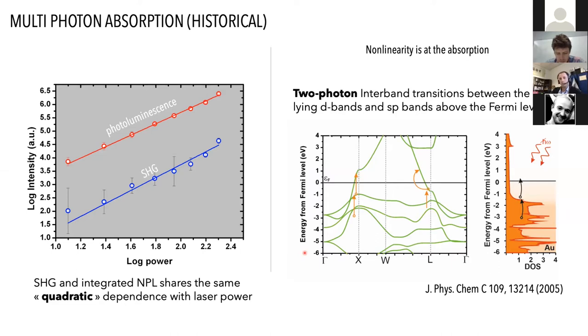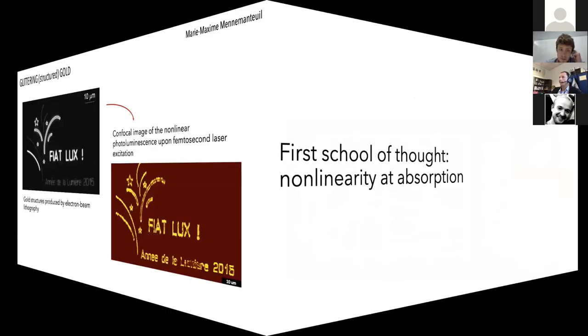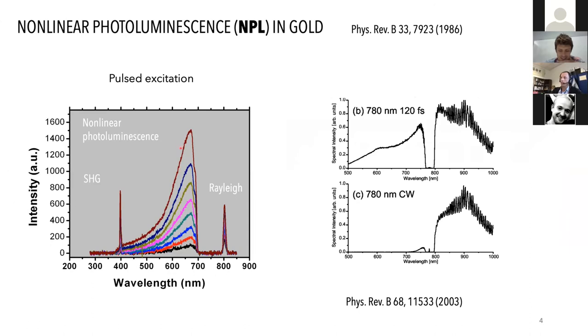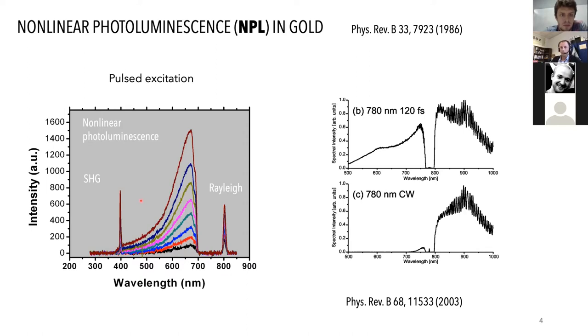Yeah, this is a good question. Usually people were actually doing this. So let me go back a few more slides. So basically here you have different ways of doing this. And the most common way is using a single pixel photodetector, like an avalanche photodiode. So you have a filter that basically removes the second harmonic, and you integrate all of the signal onto your detector. I ramp up the laser power and measure the integrated counts you have, and then you can plot the graph. And usually when you do this, you end up with a quadratic dependence or close to a quadratic dependence.